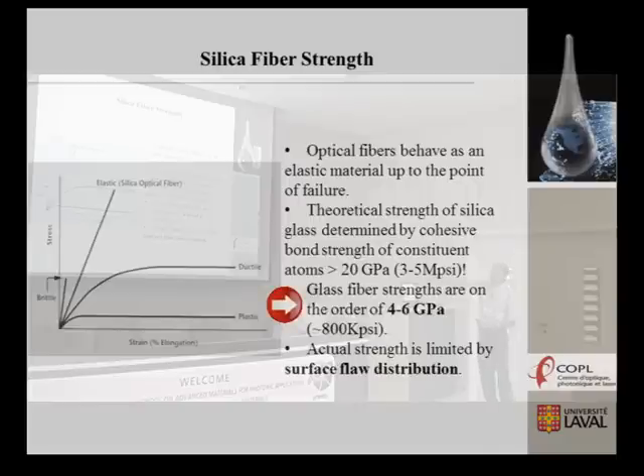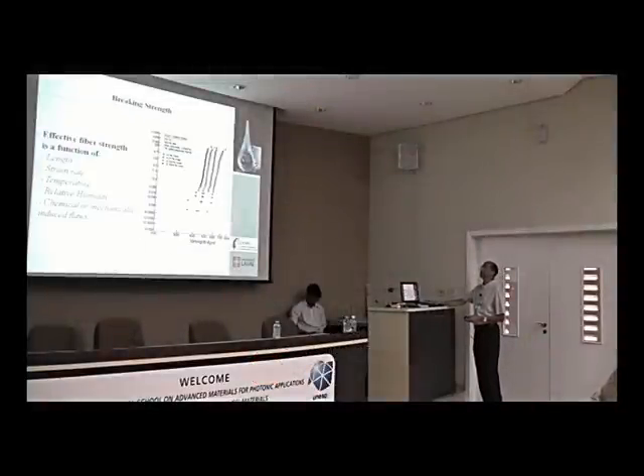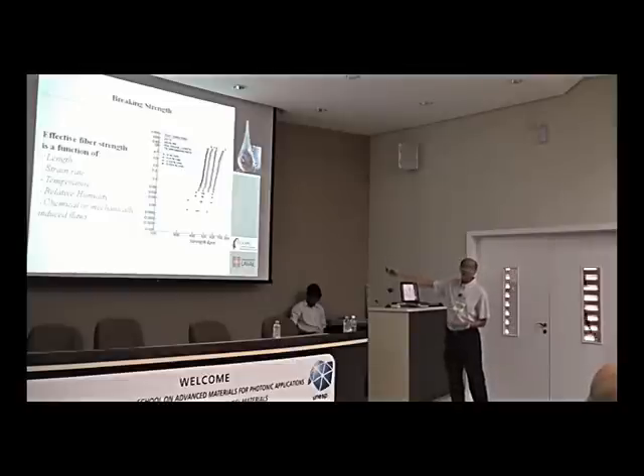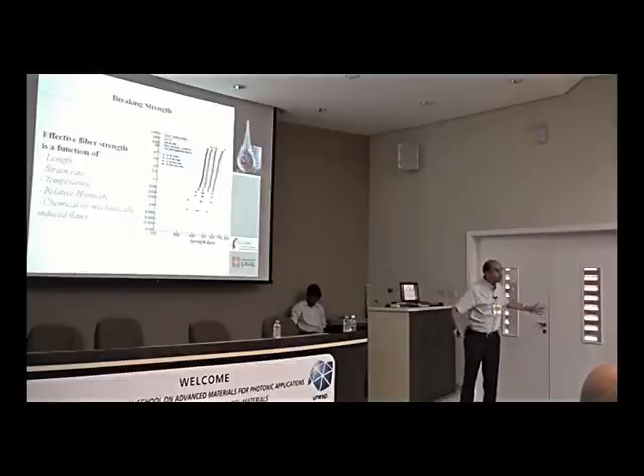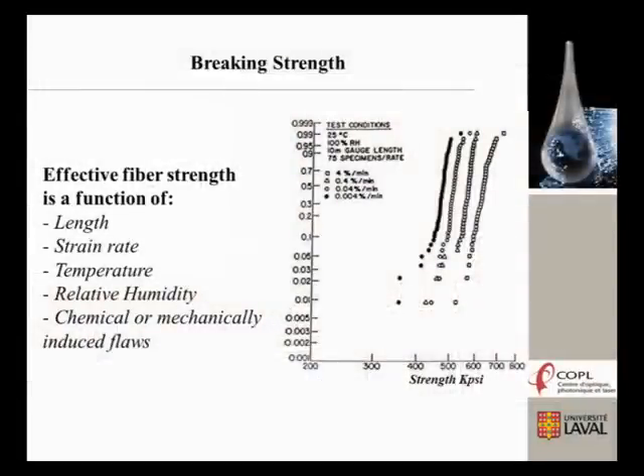And the main problem of that, we haven't time to discuss deeply on that. The main problem is surface flaw distribution. And there are several theories on that. There is one theory based on statistic measurement, and there are some people just working on that all the time in the way to specify how to get a higher quality of mechanical property of the fiber. And one of the things that they did when they measured that, because this strength of the fiber will depend on the length. If we are talking about 20 kilometers, 1 kilometer is different behavior. Strain rate, the temperature, what is the relative humidity that we are talking about, and finally, what is the chemical and mechanical induced flaw in your surface of the fiber.